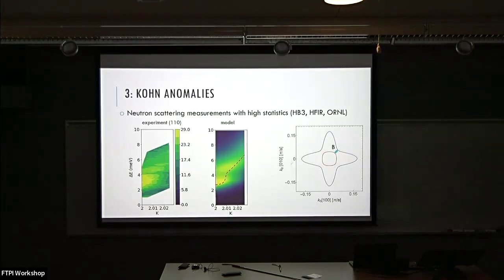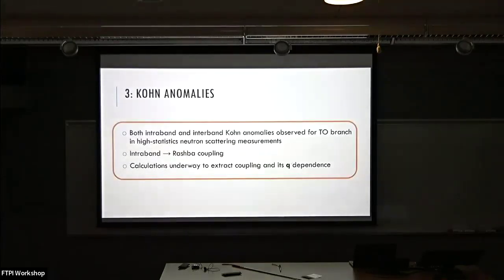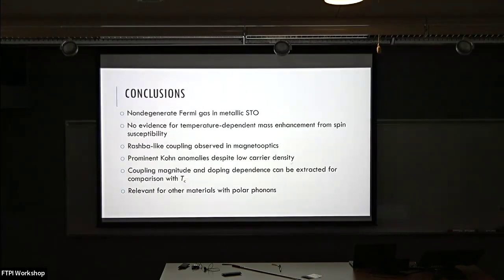Now, of course, you can go to different doping levels, do the same kind of measurement and trace it with doping and so on. I think for the first time, we actually have a method to extract these couplings. To summarize the neutrons, there are definitely Kohn anomalies, and these interband ones should be due to the large coupling. It should be possible to extract it and compare also to the magnitude from optics. With this, I conclude and thank you.